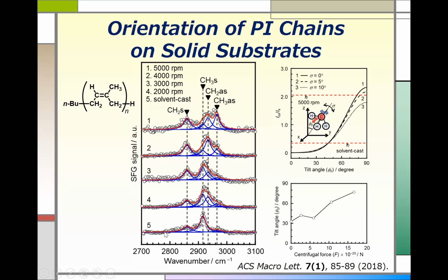And you see that the shape of number five is totally different from number one. So it's clear that polyisoprene prepared by the solvent casting method has a different conformation on the substrate from the spin coating method with a rotation speed of 5,000 RPM. And again, imagine that the substrate is going to be rotated. So polyisoprene must feel centrifugal force on the solid substrate and polymer chains are aligned.